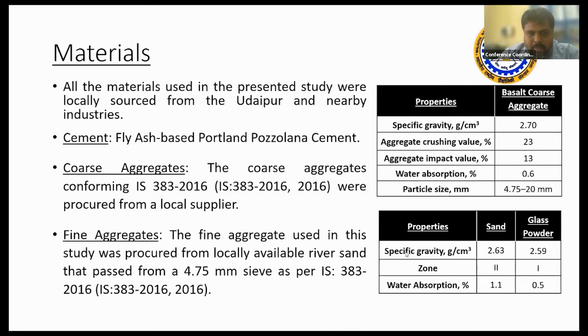The third part is materials. All the materials used in the present study were locally sourced from Udaipur and nearby industries. The cement used was fly ash based Portland pozzolan cement (PPC). Coarse aggregates used were conforming to Indian Standard 383 and were procured from a local supplier. We also did some tests on coarse aggregates like specific gravity, crushing value, impact value, and water absorption, and the results are given in the table on the right hand side.